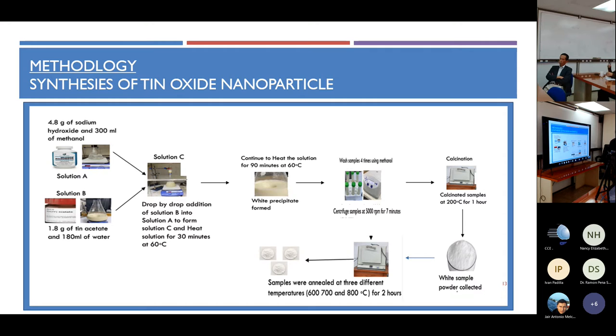The white precipitate is collected and washed 4 times with methanol using a centrifuge at 5,000 RPM for 7 minutes. Then the sample is collected and calcinated at 200 degrees Celsius for 1 hour. The white sample is then divided into three, and each sample is annealed at 600, 700, or 800 degrees Celsius for 2 hours. So I get three samples with three different temperatures.